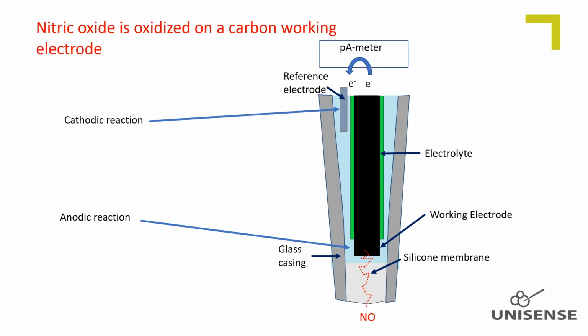The design is optimized to get the highest possible signal to ensure lowest possible detection limit. Nitric oxide is normally present in very low concentration in natural samples, and therefore the membrane is made wide and short to ensure largest possible flux of nitric oxide from the sample to the working electrode. The consumption rate of nitric oxide by the sensor is therefore high, which induces a high stirring sensitivity. The nitric oxide oxidation capacity of the working electrode is not very high, and combined with a large influx of nitric oxide per concentration unit into the sensor makes the linear range very small.